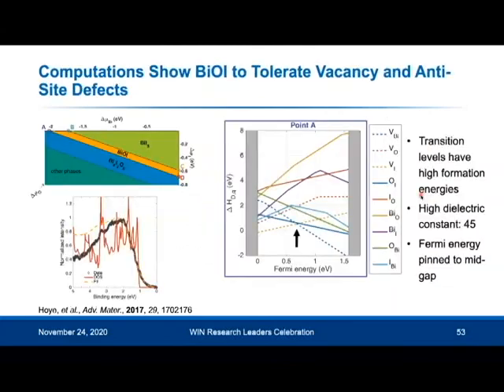We next looked at the defect tolerance, and these calculations were done by one of the PhD students I worked with at MIT, so that was Rachel Kurchin, who also worked with Vladan Stevanovic, based at the National Renewable Energy Lab. And what they calculated was the defect formation energy, and that's because the concentration of a defect has an Arrhenius relationship to the defect formation energy. If this formation energy is larger, the concentration of the defect is smaller.